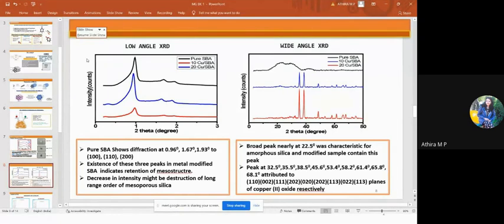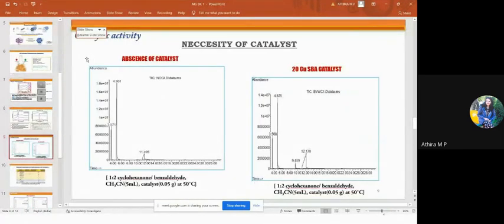However, there was no notable change in the d-spacing value for the modified system. Next is the wide angle XRD pattern. The broad peak at 2 theta around 22.5 degree corresponds to amorphous silica, and all modified samples contain this peak. The intensity of this peak diminished due to the metal content, and the prepared system contains peaks corresponding to the monoclinic structure of copper oxide, which is attributed to the presence of copper oxide on the silica SBA-15.